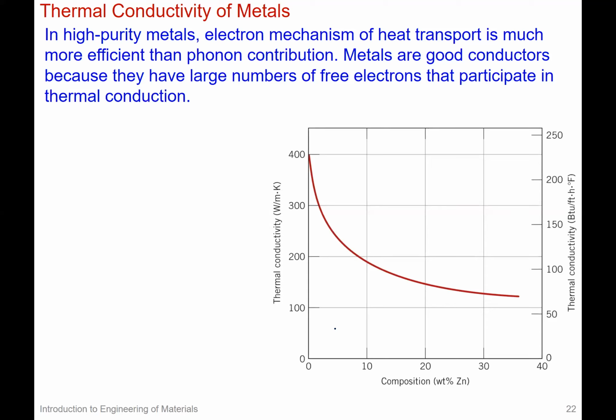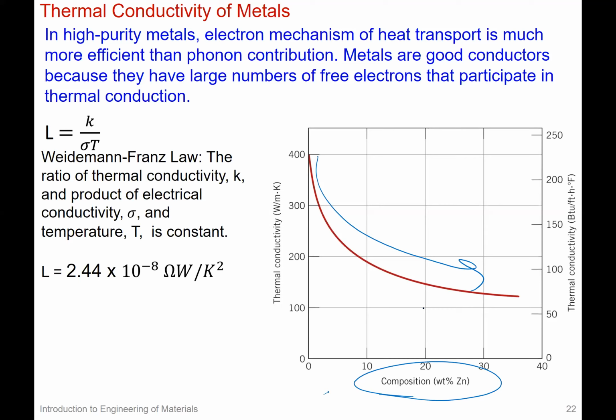Now, if you have introduced other elements into the system, you have substitutional atoms. You see here the thermal conductivity decreases as a function of increasing zinc in some other metal matrix, as you increase the composition and alloy the material more. There's a rule called the Wiedemann-Franz law that gives you the relationship between the electrical conductivity, the thermal conductivity, and the temperature. For these types of materials, it's mostly constant. It really hovers around this value, 2.44 times 10 to the negative 8. What you see reported in your book and elsewhere is that it hovers around these numbers, maybe by a factor of 2, but the magnitude is going to be the same.